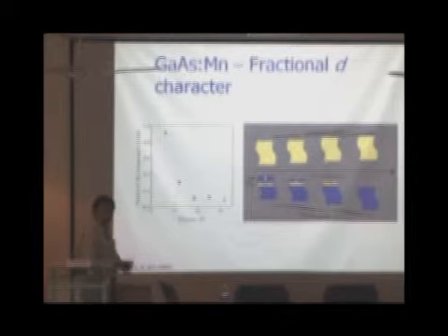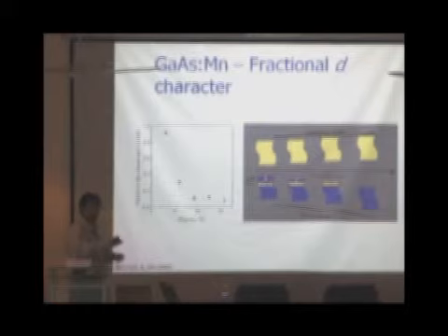And as you keep on changing the size of these particles, you're essentially increasing the band gap, but you cannot do anything with the manganese d levels. They're already atomic in nature, so they will not shift. There's no confinement effect on those things. They are already, so as to say, confined.